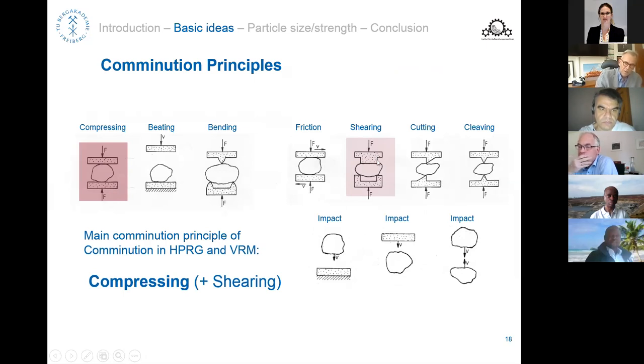But in our laboratory, we could also see, after we had removed the material layer which was pressed in between the studs, which is the so-called autogenous wear protection, very clear signs underneath that this autogenous material layer under pressure is even pushed and sliding over the surface, which was quite interesting because we found clear signs of wear underneath the surface.